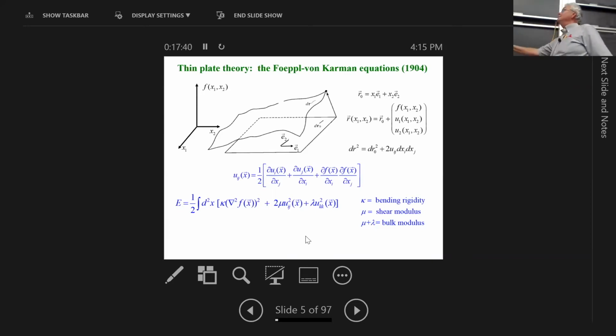And if you ask yourself, what happens to this little reference line segment on the reference sheet once it gets thermally excited, it typically gets longer, or maybe shorter, when it gets a little bit crumpled by escaping into the third dimension, and courtesy of the in-plane phonons as well. And then you can work out what happens to the metric when this occurs, and it's described by a strain tensor. Standard thing in elasticity theory, but here it's highly nonlinear. So the strain tensor that comes out of this little exercise has symmetrized derivatives of in-plane phonons, but it also has this strange nonlinear term that depends on the out-of-plane displacement F.